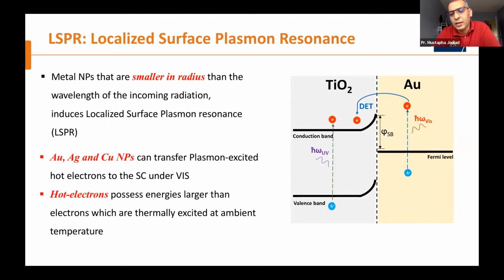The next part is just to show you technically how it works. On the right, this diagram shows titania and also gold. When you have the interface between this dielectric and this metal, we excite the electrons in the gold. They are excited; this is what we call hot electrons, and they are able to jump above the Fermi level to reach the conduction band in titania. This phenomenon is known as LSPR, localized surface plasmon resonance. So the whole process that we have done is to make this device, check first the performance of the device, then explain why the performance is good due to LSPR.